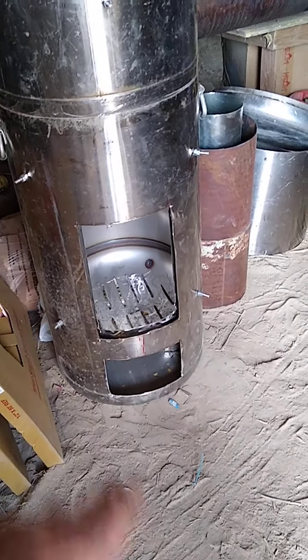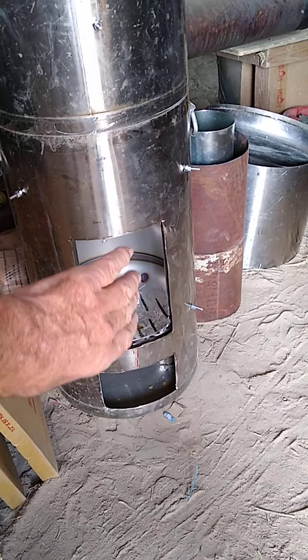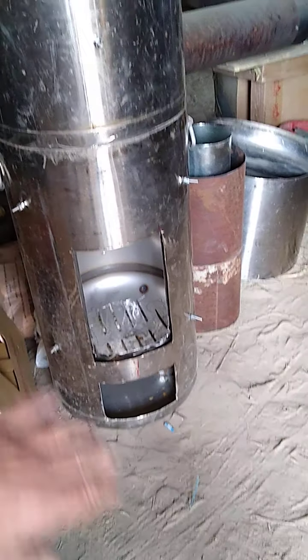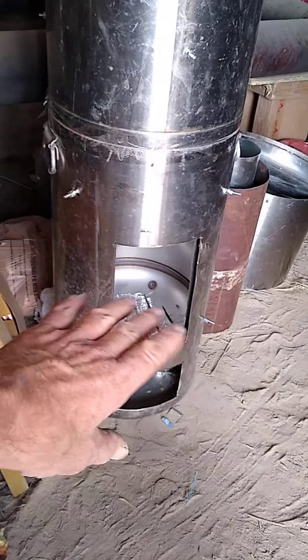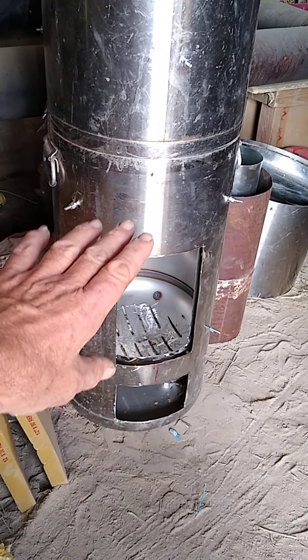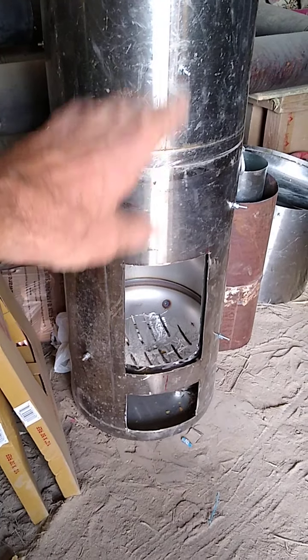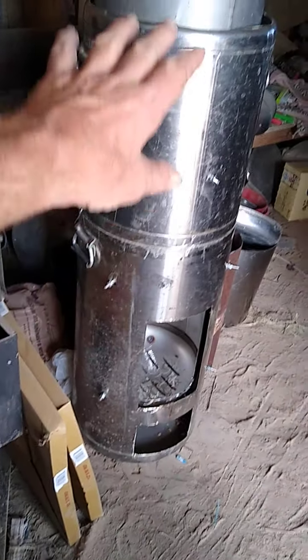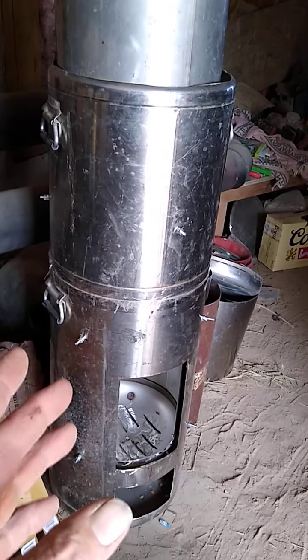I finished up the grate, like I said, the ash pan, and the little bolts here keep it centered, the inside tank from the outside tank. It's air insulated right now, but I'm going to backfill it with, if I can get this right, calcium silicate on the lower section. It's a low temperature concrete mix, like conventional concrete. Then from about here and above I'll go over with calcium aluminate, and it'll handle the higher temperature up through the thimble. The thimble will all be calcium aluminate.